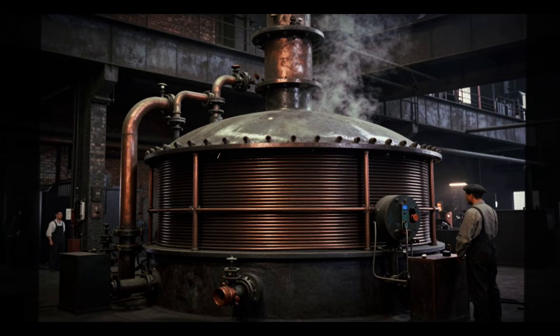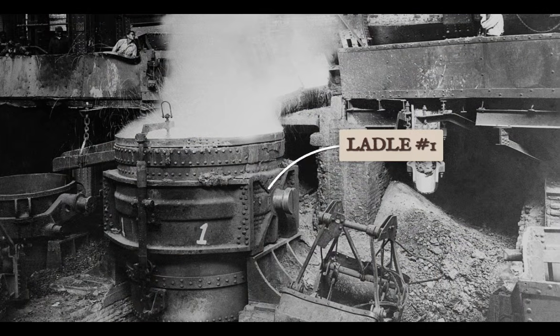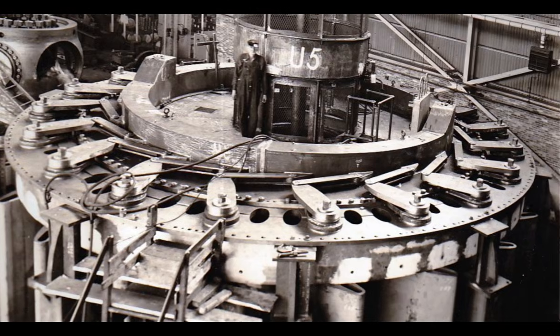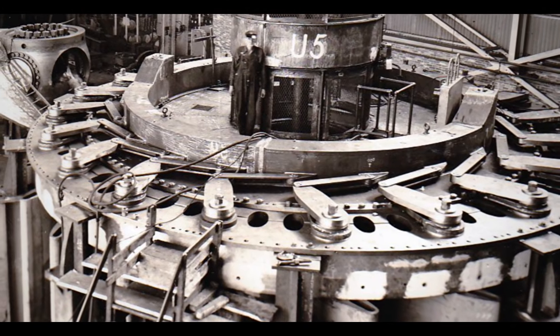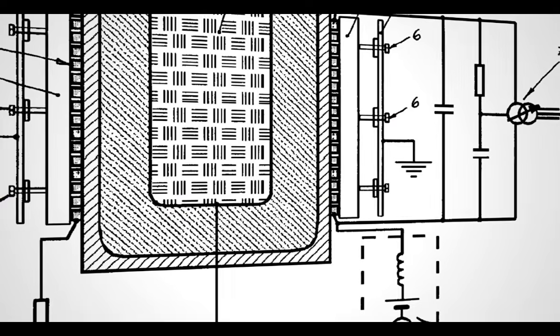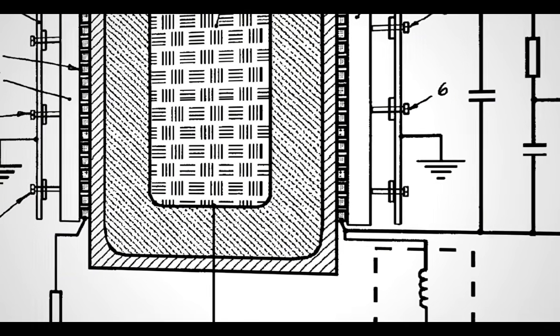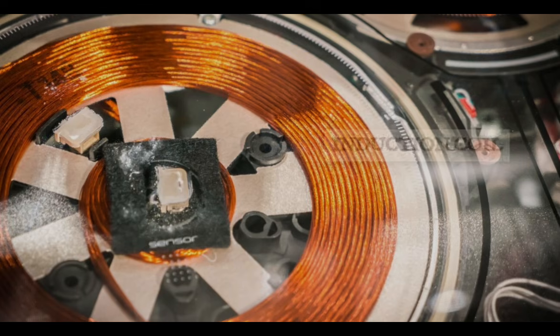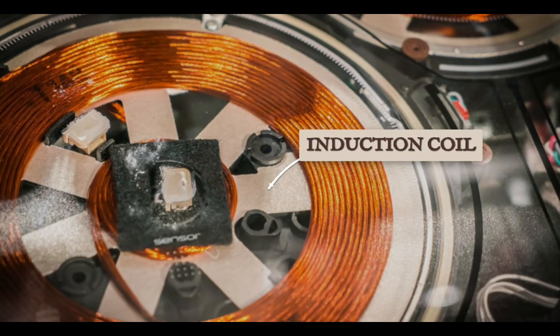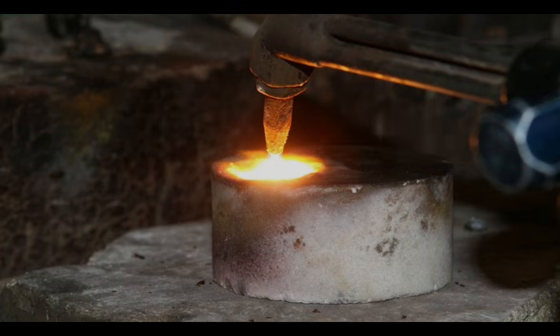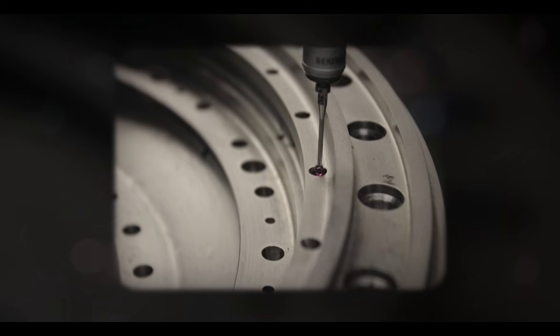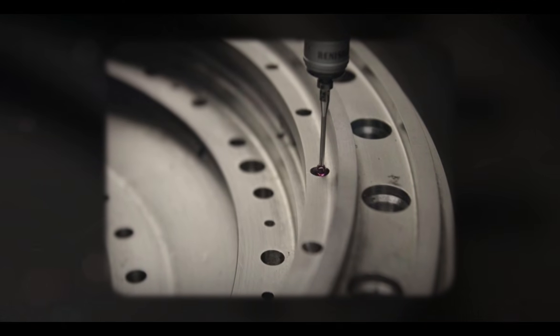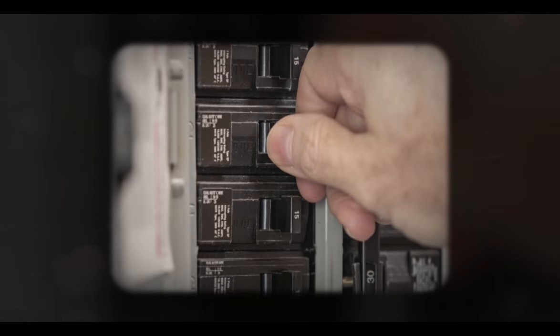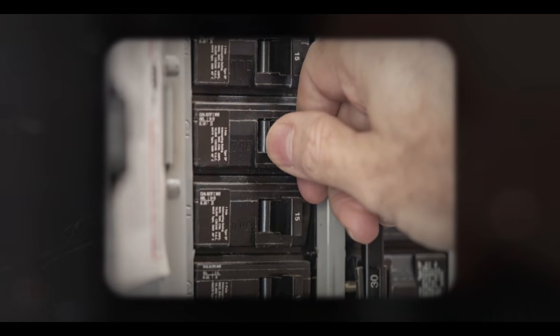What induction furnaces in the 1920s did not have was a ground leak detection system. Modern induction furnaces incorporate a probe in the bottom of the furnace lining connected to the electrical ground that detects when metal has penetrated the refractory to within a measurable distance of the coil and shuts off power before the breach is complete. The system works by monitoring the electrical continuity between the molten bath and the probe. When the metal touches the probe, the circuit closes, the detector registers the contact, and the power supply cuts off.